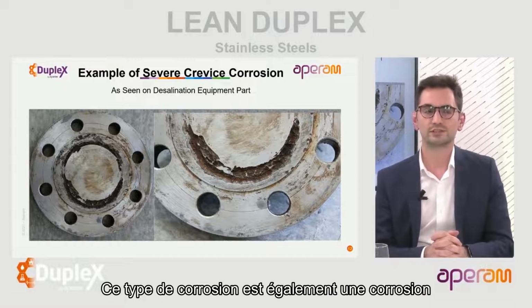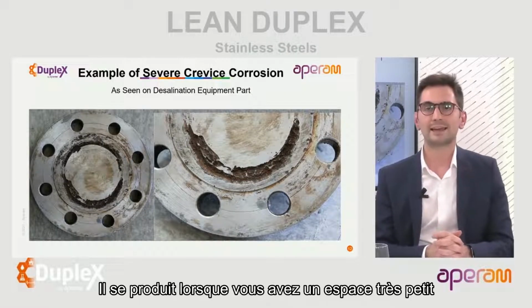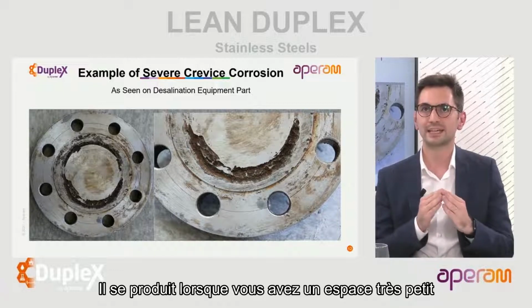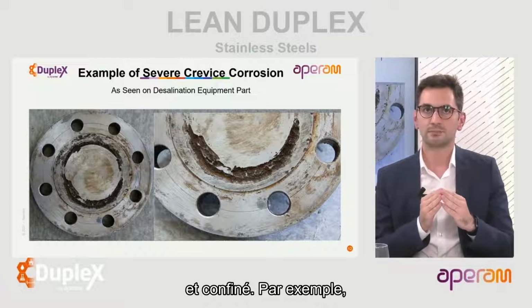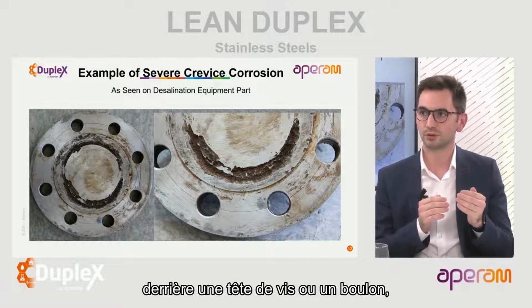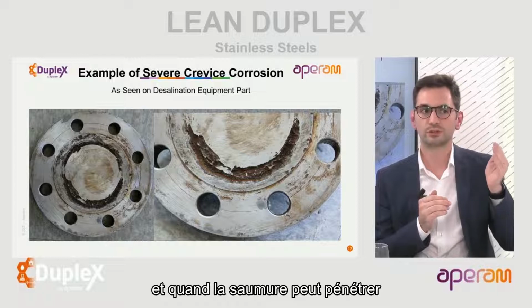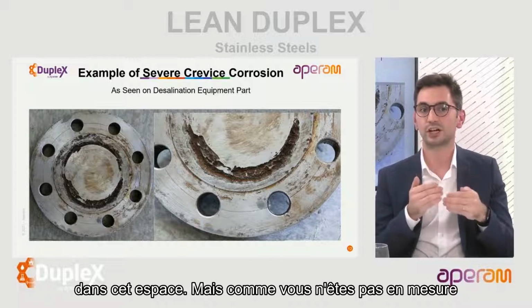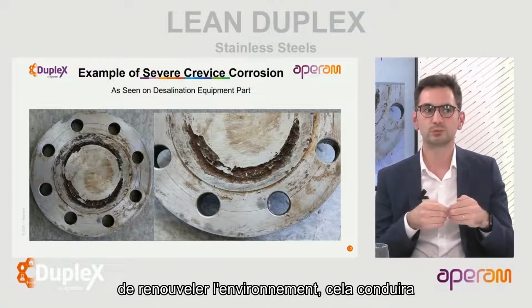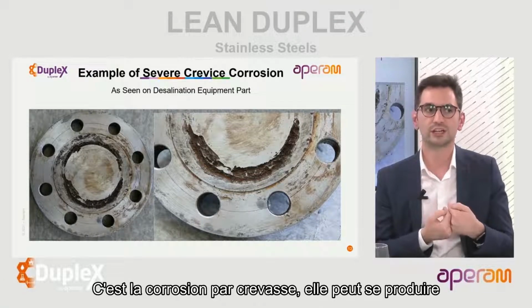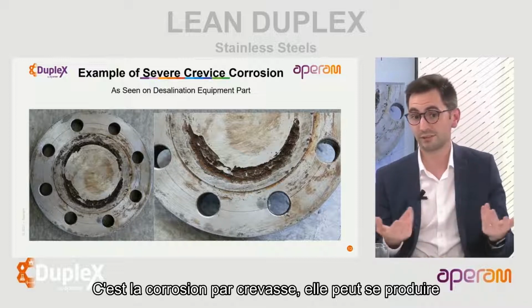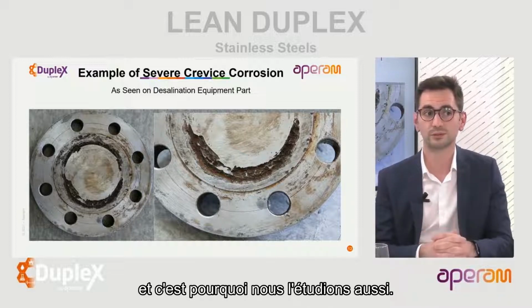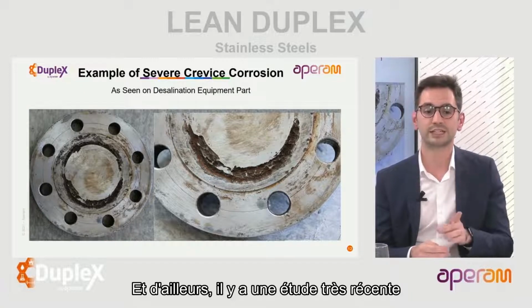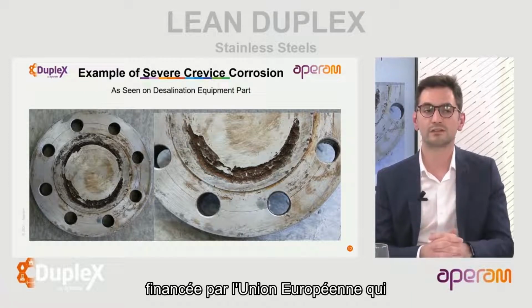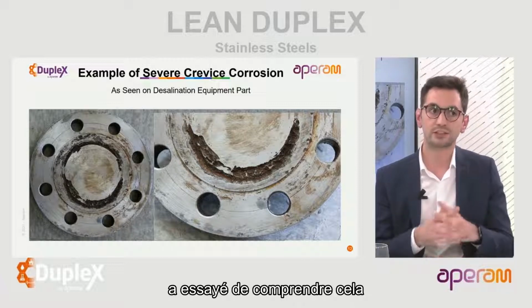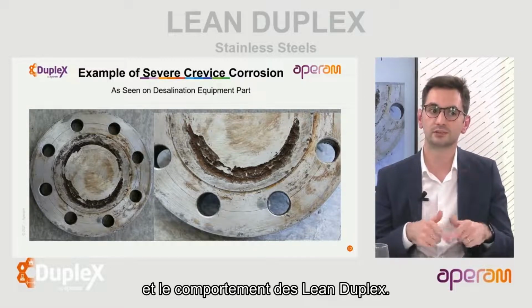This type of corrosion is also a localized corrosion. It happens when you have a very tiny and confined space, for example, behind a screw head or a bolt. And when the brine is able to go inside that space, but since you're not able to renew the environment, it will lead to a very severe type of corrosion. So that's crevice corrosion. It can happen, and that's why we also study it. And by the way, there is a very recent study funded by the European Union that tried to understand this and also understand it using Lean Duplexes.